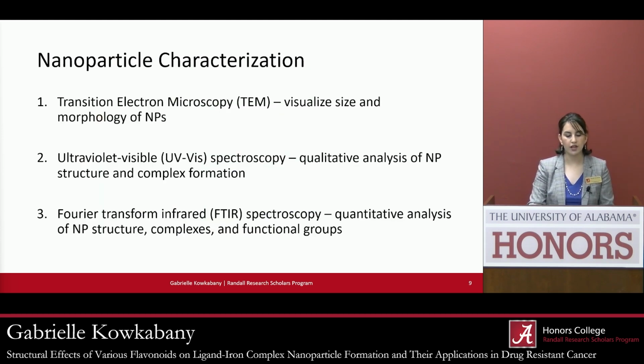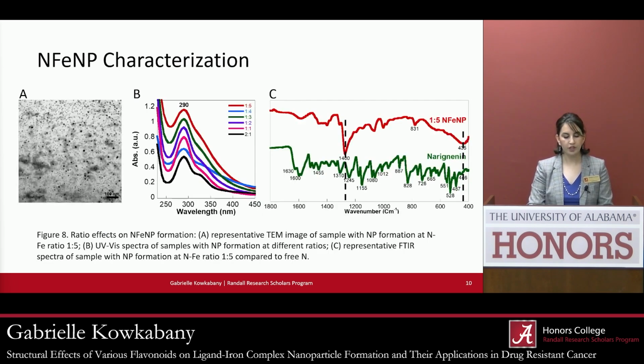In order to characterize these nanoparticles, I used transmission electron microscopy in order to visualize the size and morphology of the nanoparticles. I used UV-vis spectroscopy and FTIR as well. So this is the characterization of my nanoparticles using naringenin. And so in part A of this figure, you can see the TEM image taken.